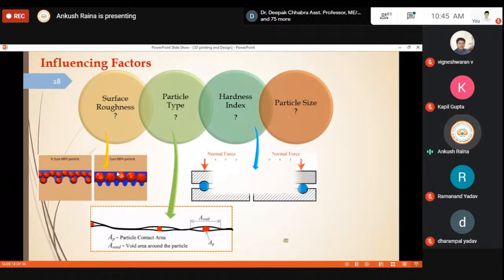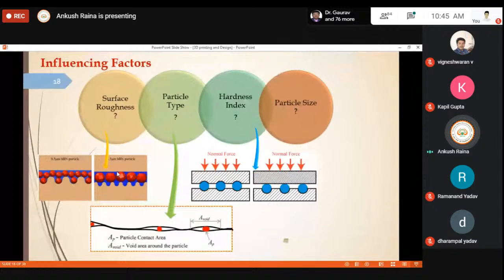Then the hardness index plays an important role. Hardness index means the ratio of the hardness of the particle to that of the surface. In these two figures, you can see that the hardness of both surfaces is the same, but it is less in comparison to the particle. So the hard particle is being embedded in both these surfaces. But on the other hand, here the topmost surface is harder in nature and this one is softer, so the particle is not embedding in the topmost surface, it is embedding in the lowermost surface only. So the hardness index is an important aspect, whether the material is soft or hard, and what kind of nanoparticle we are using, that is also an influencing factor.